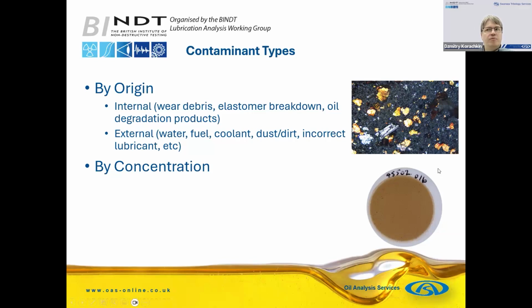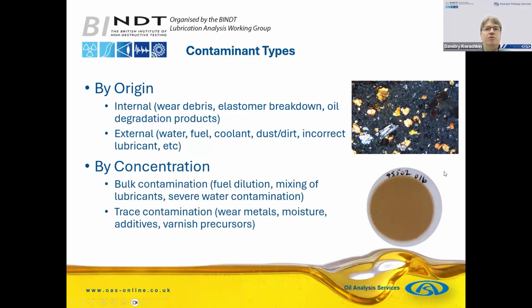And another way to look at contaminant is by concentration. Is it bulk contamination? You know, we have 10% fuel in this oil. Is it a mixture of different lubricants? We have 50% of one lubricant, 50% of another lubricant, a lot of water getting in. Those are often obvious. There are significant effects on many properties, but also sometimes you can visibly see two layers within the sample, where at the bottom you have maybe a layer of water or a layer of different lubricant that has different densities, so they separate, so things can be obvious.